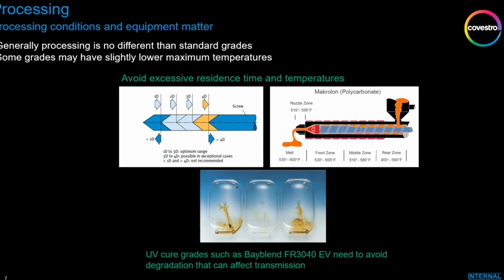Plastic materials don't like to sit in hot temperatures for very long. If your molding machine is not designed properly, if it's not spec'd properly to the size of the part, then you can end up with the material sitting in the barrels and cooking for very long periods of time. The net result is what you'll see in those lower pictures: discolorations, burned material, brown material. Those things look bad, they're cosmetic issues, but they can also give you serious performance issues as well.